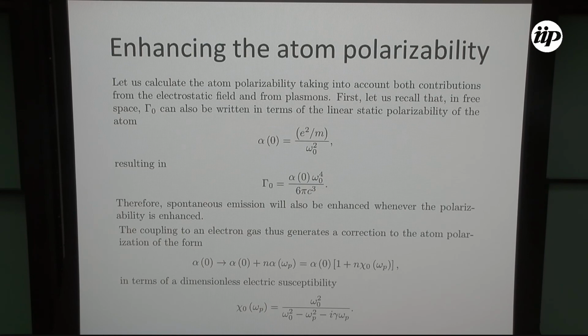Well, this is not the whole story. Now my atom is inside a medium. So I have to look at what happens to the atomic polarizability inside the medium. Fortunately, the spontaneous emission rate can be written in terms of the linear static polarizability of the atom in this fashion. And now I have a dipole with a typical oscillation frequency, and I have a metal with a typical plasmon frequency.